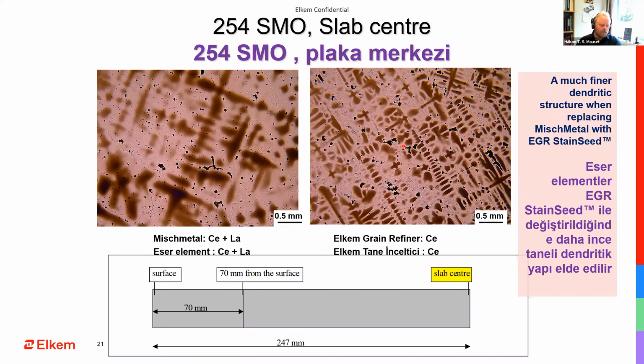And what they actually saw was that normally this steel mill had a lot of problems when they were forging these ingots into bars. They got a lot of cracking during forging, and they had to do a lot of grinding of the ingot and also the forged bars. So it took a lot of time, and they lost a lot of money when producing these grades. But when they started to use the EGR Stainseed, they had no problems anymore with cracking during forging.